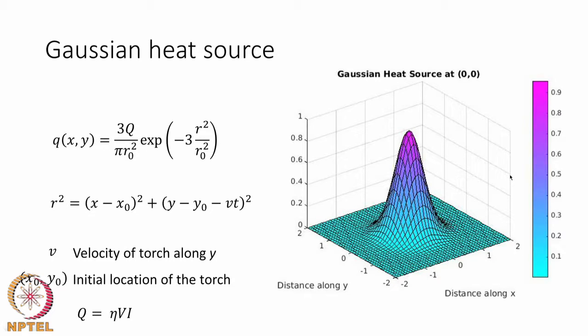And as you can see, we can actually mathematically represent the heat source that we have seen in the previous slide by using what is called a Gaussian function. So, the function itself is shown to you here, written exponentially in a form that goes as e raised to the power of minus x square, where x is the length, and in 2D you have not just one length, but you have 2 directions. So, you use the radius as a parameter r. So, you have e raised to the power of minus r square as a general nature by which the intensity is decreasing as you go away from the center of the heat source, and we have those numbers like 3 that are given to ensure that the variation is as sharp as what is normally seen in the actual arc,